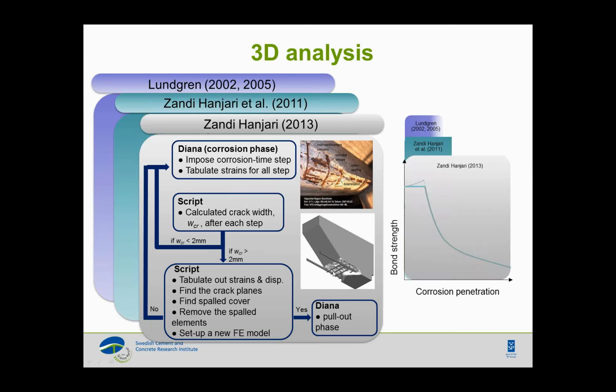Having this computational scheme, we manage to go even further, because as soon as we have large crack widths and we have cover delamination, just before we run into numerical problems, we deactivate the elements. And that allows us to go for larger corrosion penetration, meaning that we go for higher swelling effects of corrosion products. And we have actually validated that with quite a few specimens, which I'm not showing here.